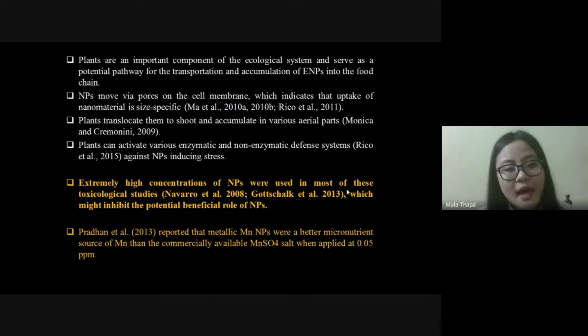But extremely high concentration of nanoparticles were used in most of the toxicological studies, which might inhibit the potential beneficial role of nanoparticle. For example, there are many studies which show the beneficial properties of nanoparticle as well. For example, in 2013, Pradhan et al. reported that metallic manganese nanoparticles were a better micronutrient source of manganese than the commercially available manganese salt.